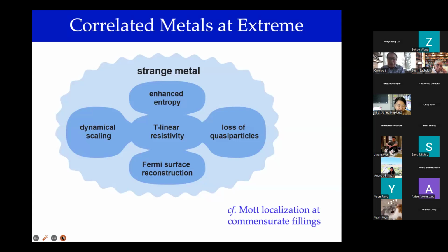In many ways, strange metals represent the extreme form of correlated metals. One could make the analogy that when the interactions become strong at commensurate fillings in lattice settings, it's well known that localization can happen, but even when the system stays metallic, there's some extreme effect of correlations. The most famous one that has been known the longest is the T-linear resistivity, but there's been increasing recognition that there's a slew of other properties such as dynamical scaling, Fermi surface reconstruction, loss of quasiparticles, and enhanced entropy among them as part of the characteristics of strange metallicity. And I'll come back to some of these.